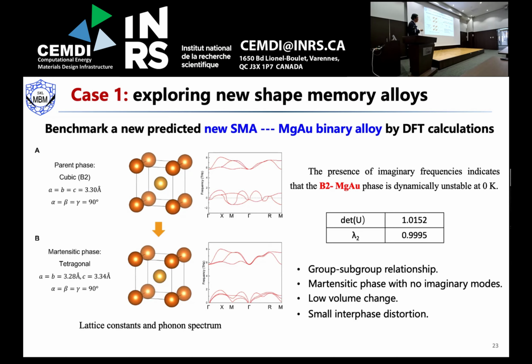And we also calculate lambda 2. That means the interface distortion. And the lambda 2 is very close to 1. I mean, lambda 2 equals 1. That means the lattice interface distortion is 0. So for this alloy, we found the four properties.